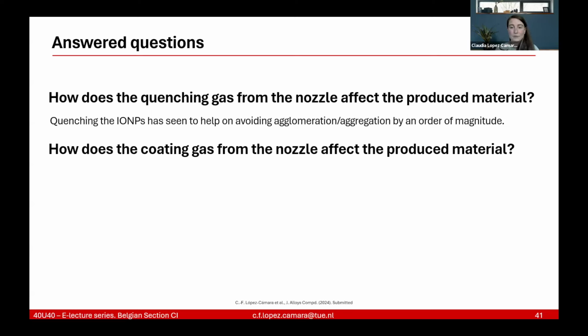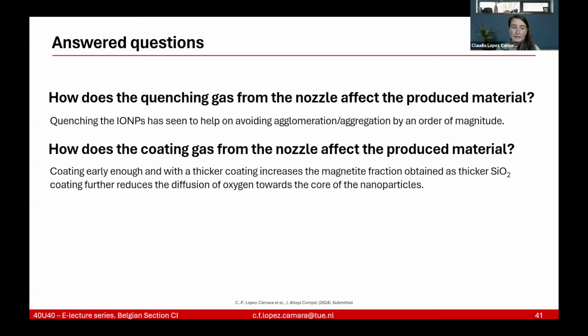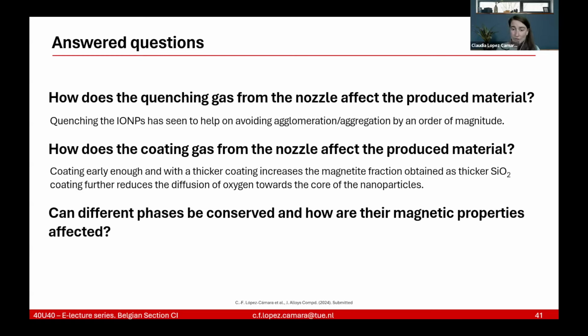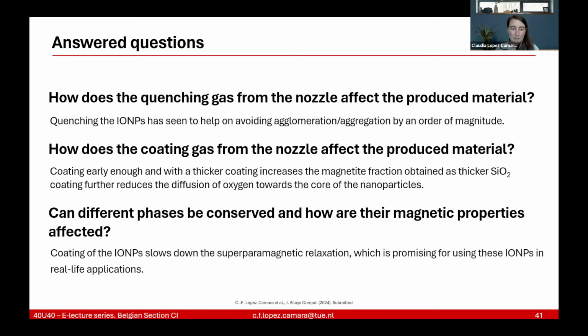How does the coating gas from the nozzle affect the produced material? We saw that coating early enough and with a thicker coating increased the magnetite fraction obtained, as thicker silica coating was further reducing the diffusion of oxygen towards the core of the nanoparticles, which means that the core of the nanoparticles were staying less oxidized, let's say. And can different phases be conserved, and how are their magnetic properties affected? That's something that I did not really fully explain here, but basically the coating of iron oxide nanoparticles slows down the superparamagnetic relaxation, which is promising for the use of these nanoparticles in real-life applications.